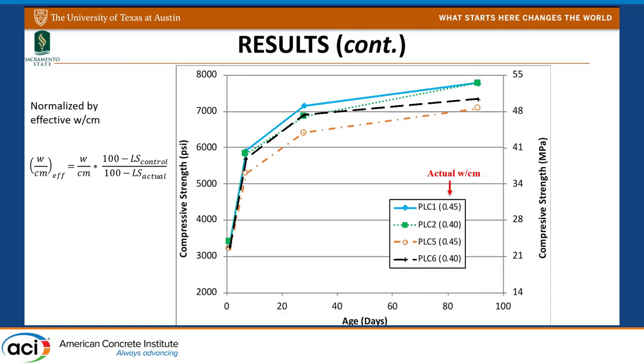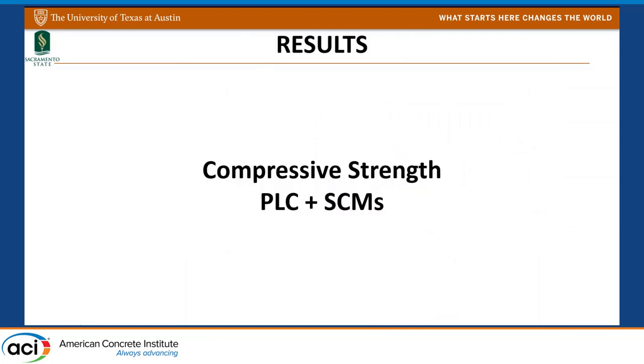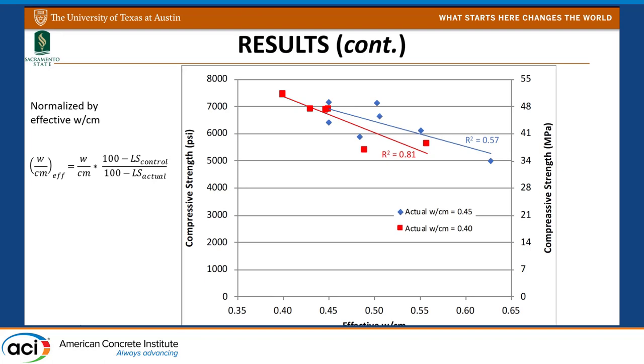We also looked at the effective water-to-cement ratio by normalizing for the amount of limestone present. All of these mixes have approximately the same effective water-to-cement ratio due to the increasing limestone content, and you can see they're all approximately equal in terms of compressive strength. We plotted compressive strength as a function of effective water-to-cement ratio and got a reasonable trend line at 0.4, though it was less clear at the higher water-to-cement ratio.